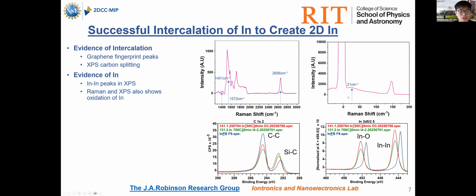we do have some issue here. So as we intercalate and do Raman to try to locate the indium signal, what we see is actually a big bump near this wavelength, because this contributes from the indium oxide.